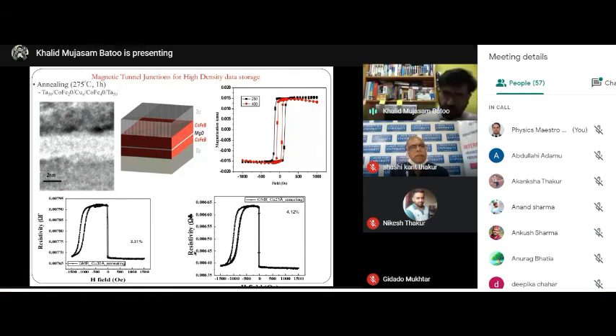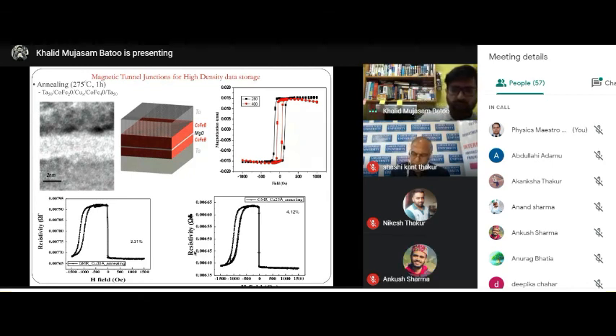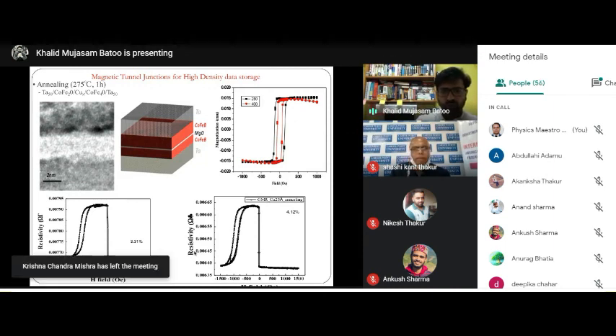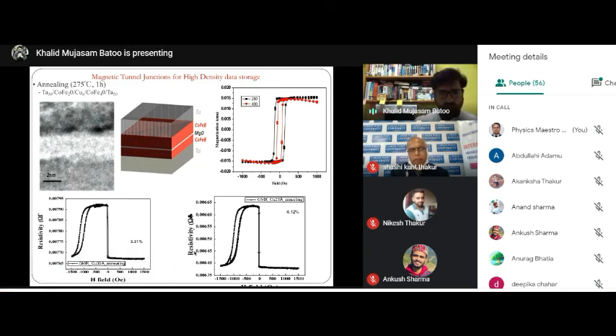We have designed multi-junction materials, tunnel junctions for high density data storage, in two ways. One, we try to use magnesium oxide as an insulating layer. We also use copper as a conducting layer, while magnesium oxide is insulating in a different way.